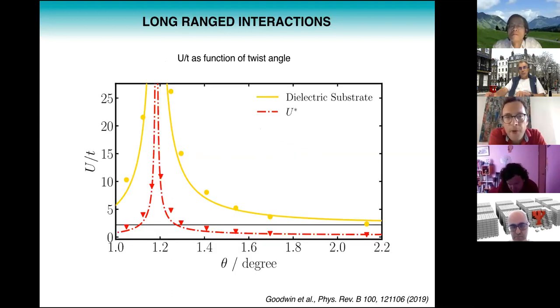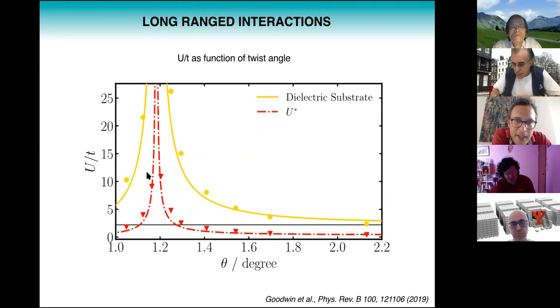So now, of course, we can easily calculate U star from our extended Hubbard parameters, and when we plot U star over T, we get this red line. You see now this red line is only in a small twist angle window above the critical U over T, which is in much better agreement with experiment, which only sees strong correlation phenomena in a small twist angle window close to the magic angle.